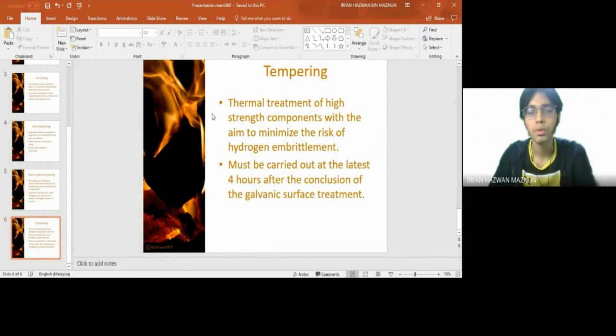Tempering is the thermal treatment of high strength components, where the strength is above 1000 megapascal or hardness above 320 HV, with the aim to minimize the risk of hydrogen embrittlement. Tempering must be carried out at the latest 4 hours after the conclusion of the galvanic surface treatment. The minimum temperature depends on the strength classes or on the materials that are used.